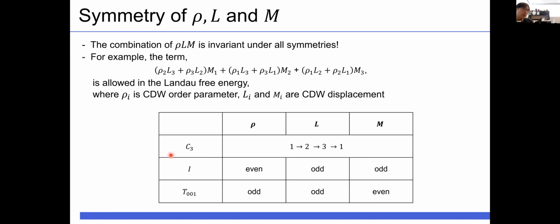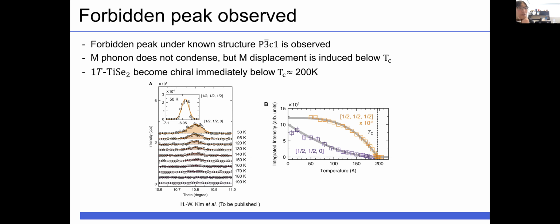So we can consider the additional term in the Landau free energy, and this term can induce M displacement when L and rho become non-zero. This is how inversion symmetry is broken in 1T titanium diselenide. And we also found a forbidden CDW peak that can only be explained by M displacement. This peak is forbidden under the known structure P3 bar C1. Therefore, this is another evidence that atoms move along the M phonon eigenvector. So even if the M phonon does not condense, M displacement is induced below the critical temperature, and 1T titanium diselenide becomes chiral immediately below the known critical temperature, 200 Kelvin.